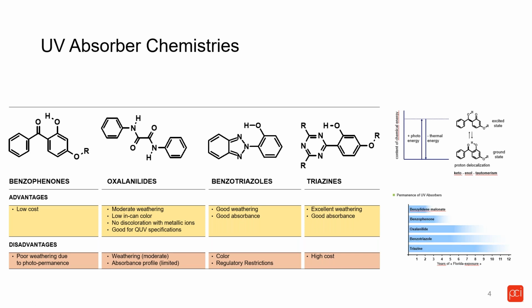If you look carefully at those molecules, you will see that they all have this double bond oxygen close to a hydrogen. And what this tells us is that the way the UV light is absorbed is by a tautomerization effect, where you have this transition of the hydrogen from the OH group to the double bond O. However, this tautomerization is not exactly the same in terms of its kinetics, as well as in terms of how it will go back to its ground state, which explains the durability of a UV absorber.